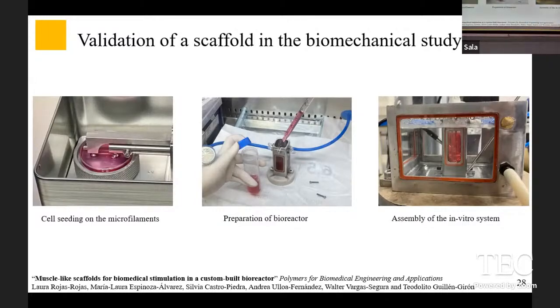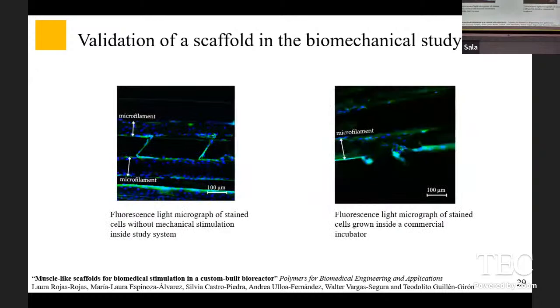And again, fortunately for us, the cells that were growing inside the study system are the same as the ones that were growing on a commercial incubator. So once again, the bioreactor is working properly. And moreover, this result shows that the scaffold is working properly as well. In these images, I'm sorry, I didn't say, the blue dots are the stained nuclei and the green is the cytoplasm of the cells, and you can see them on the surface.